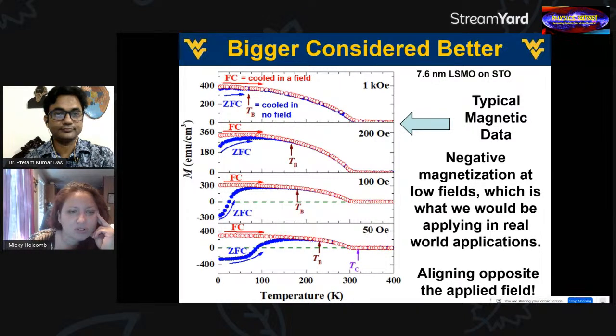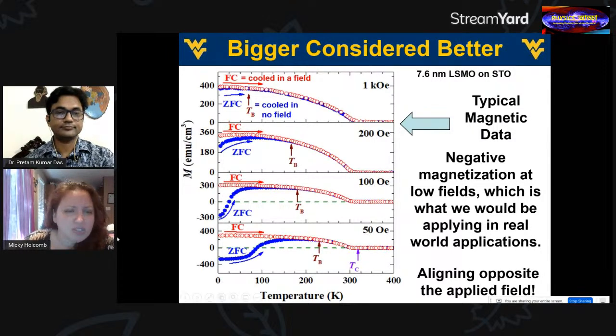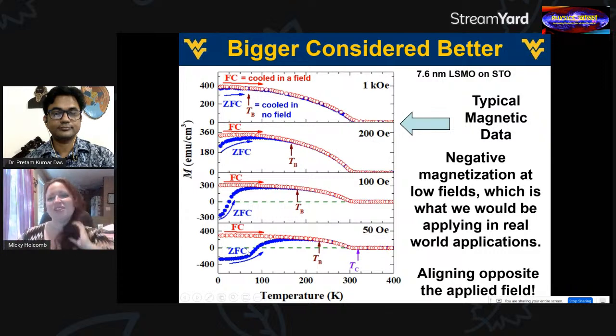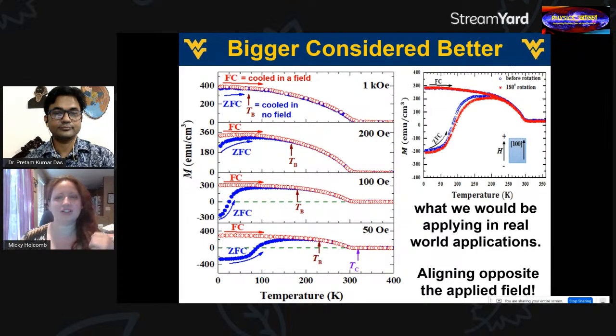But if we don't cool in a field, we actually initially see that the magnetization is negative. That means opposite to the field that we are measuring in. And not only that, but look at how strong it is. The strength is almost as strong in magnitude, if we switch the sign, as the field-cooled measurement. And it maintains for a pretty large temperature range. If I had measured this in 20 Oersted, I could get it to extend even further. So I can adjust this. We're seeing negative magnetization at these low fields. That's really interesting. That's some new kind of stuff.